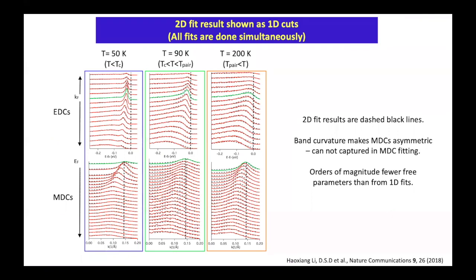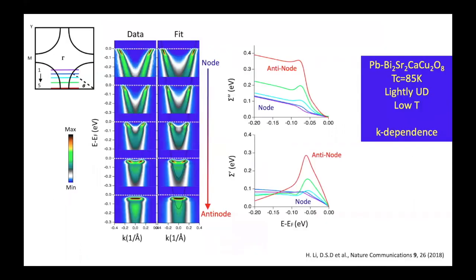If I try to fit this asymmetric thing with a Lorentzian, as I typically do, I have problems. I need to put an artificial background in. That doesn't come here. And I have orders of magnitude fewer free parameters. So we're very happy with how this works. We do it as a function of momentum throughout the Brillouin zone. Here's near the node. The self-energies are much smaller. If I go to the antinode, the self-energies are huge.